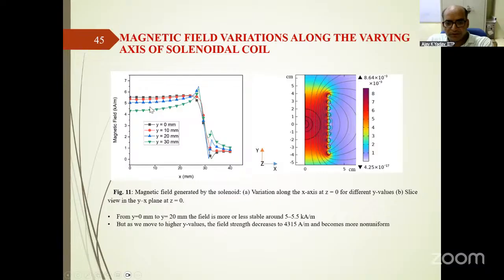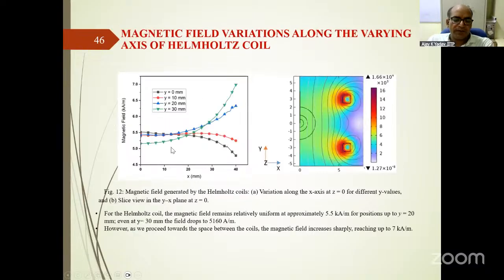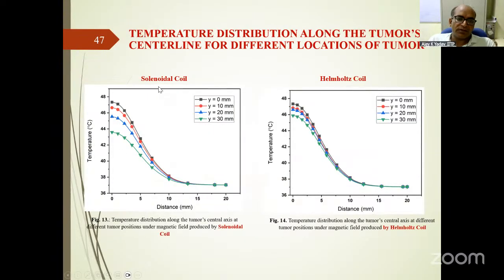If you go to the Helmholtz coil variation, you can see here this much variation is there. But this 30 mm is far away. So if you leave this 30 mm, the other variations are less compared to the solenoidal coil. If you see both together, Helmholtz and solenoidal coil variation, you can see here 30, 20, 10 and 0. How much variation is there? Same thing 30, 20, 10, 0. You can see the variation here. The temperature variation is less. So this is more effective, you can say, the Helmholtz coil. The variation of temperature is not that much, it's less.